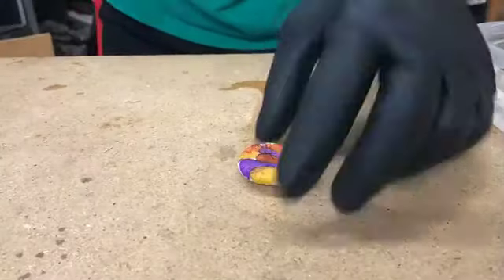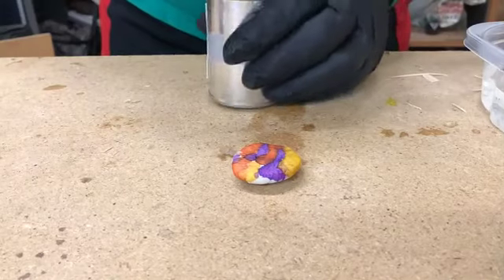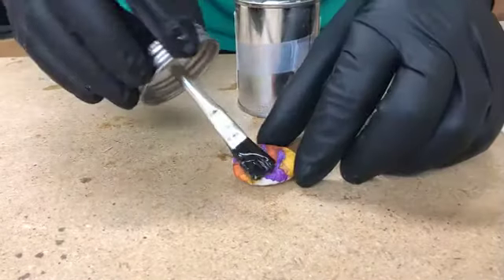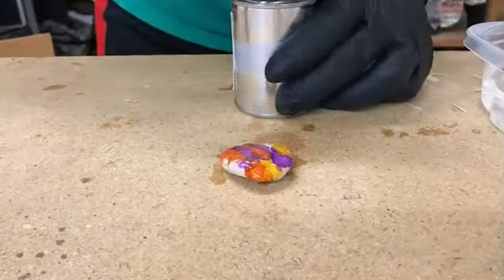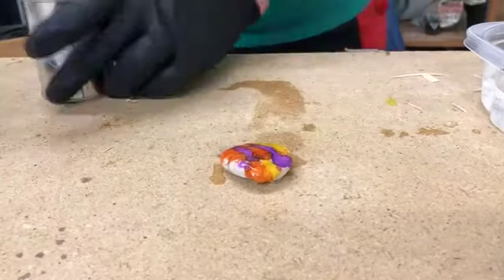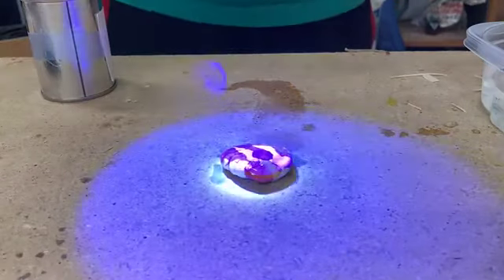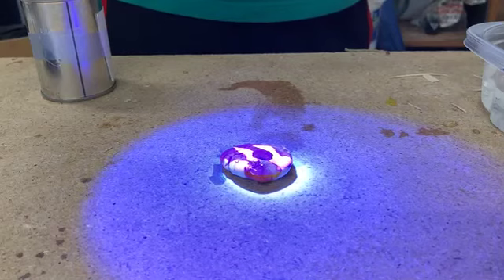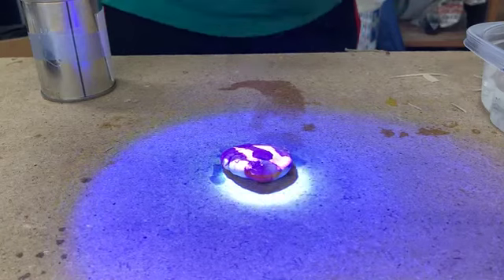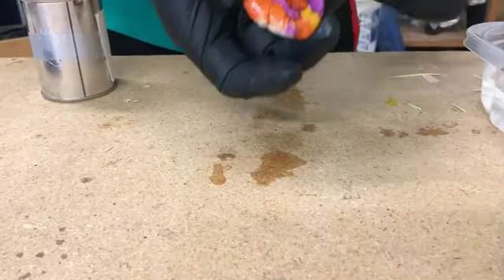Alright, that's ready. Now we want to coat it — we can make this fast and make it dry-cleanable, for example if you want to make a button or just want a glossy appearance. We're going to use a new quick cure coating and just apply it. Now in order to cure it, use a 395 nanometer black light for 10 seconds. And now we're done — we have a nice glossy material and it's complete.